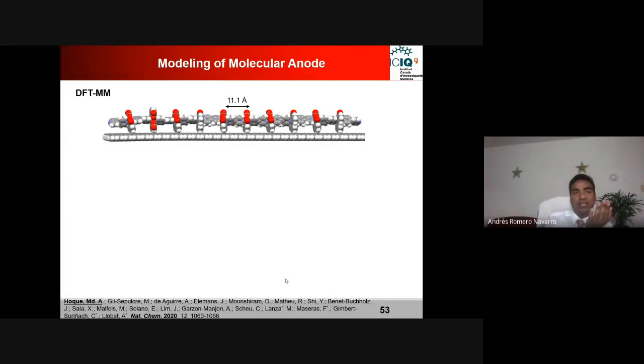And then we thought to do this modeling to understand, okay, we saw that they are perfectly aligned by this STM image. And then we were curious how, and what kind of things are happening so that they are staying that way. So we decided to do the modeling experiment. Basically, we did DFT calculations, and based on this DFT calculation, what we found is that the distance between two ruthenium units is 11.1 angstrom. But with the STM experiment, we found 10.9 angstrom. So it's a very close value. The DFT is supporting that experimental value, and the experiment is also supporting that the theory we are getting is not wrong.